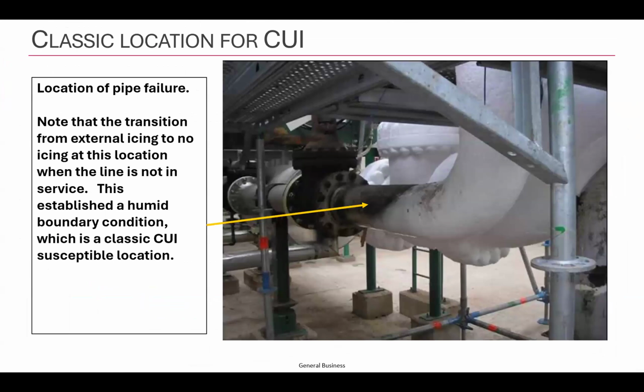So what you see here is the location where it failed. You will say, okay, it is not insulated. No, this was after we repaired it, and we did not put the insulation back on at that time. And you see there is a transition zone over there where you have a very cold surface where it's iced up. You can clearly see that now.